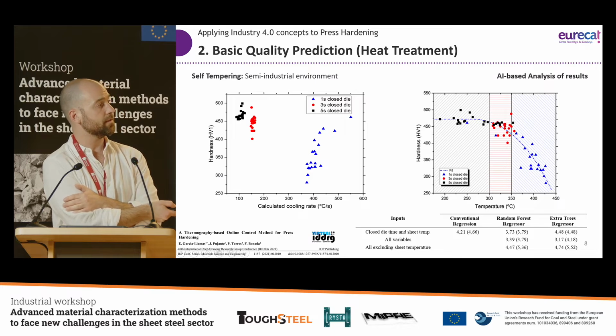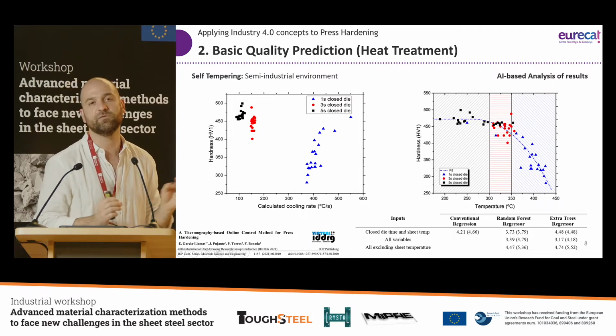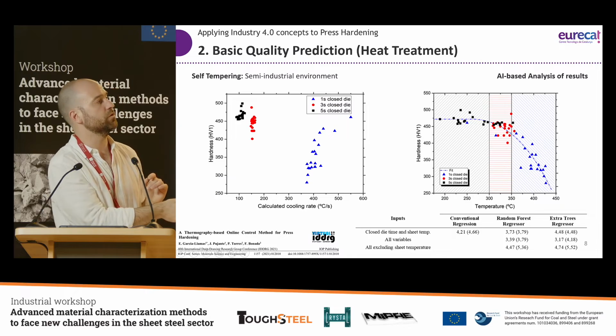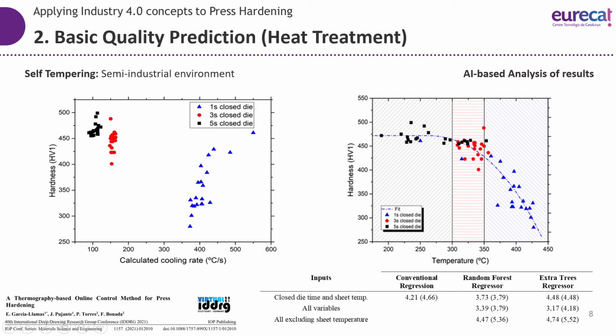Look, this is the cooling rate. This is the hardness. And what we're seeing, of course, there's a little bit of cheating here, because you see it's 1 second closed die, 3 seconds closed die, but the important parameter here is not the cooling rate. This 300 degrees per second is the sacred line that we need to cross, but this is 400 degrees per second, this is 200, and we are still having hardnesses that are below what we would expect.